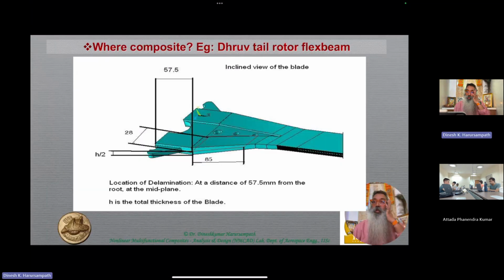Okay, so here's another schematic of the same structure, and essentially a location at which there was a delamination, for example, two layers separating out, which could be quite disastrous because then it will not be able to take the shear if the separation increases, right?